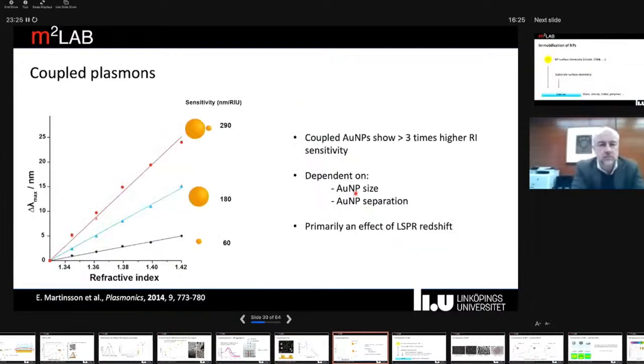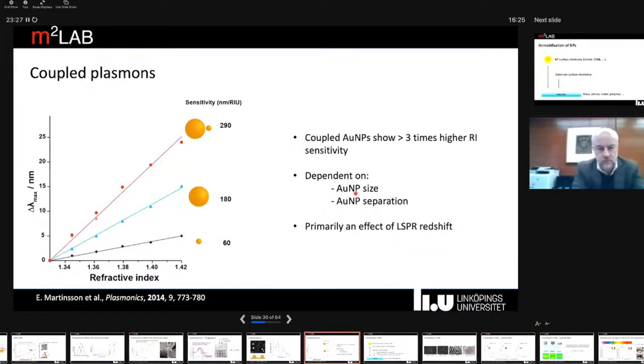And this actually gives us an increase in sensitivity with a factor of 2 to 3 compared to the individual particles. And again, primarily an effect of the redshift of the plasmon band.